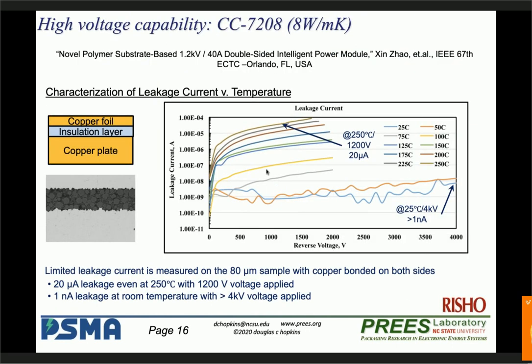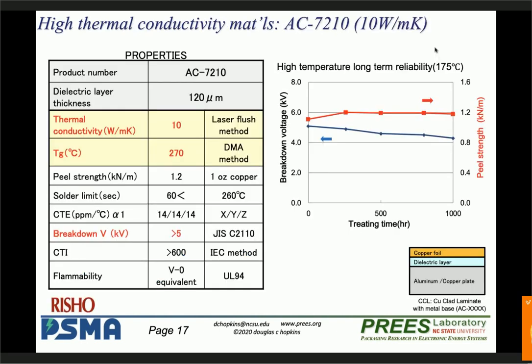This is some testing we did on leakage currents, and I won't bother going through this, but this has been published in the past. Again, we have really good low leakage current for high voltages. This is the 10 watts per meter degree K, and again, the same graph showing that for voltage withstand, it kind of drops down as we go over more time. This graph may be updated because I know that this was under development when we were doing these. So I want to say that this may actually be a better performer than what's shown right now. But again, the material does not degrade over time due to peel strength, which is critical. And this was all done on a DBC structure.